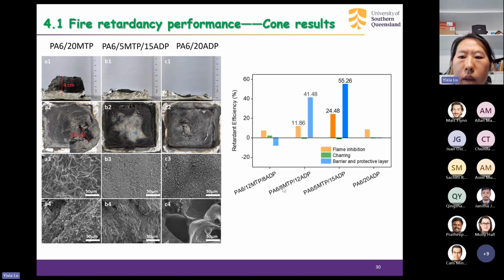But for this individual addition of 20% of ADP, from the SEM image, we can find so many holes in the internal layer. So it is not as good as the composite containing MTP. And we also investigate the fire retardant efficiency regarding flame inhibition, charring, and barrier and protective layer. These parameters show that 5% of MTP and 15% of ADP enhanced the fire safety regarding flame inhibition and especially the barrier and protective layer.